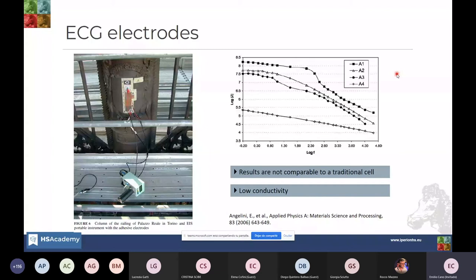And in this example, they use electrocardiogram electrodes, the ones that are used for medical studies. They were able to measure the impedance of the surface, and you can see on the right the modulus of the impedance. You can see that again they have been able to measure the impedance of different areas that have been cleaned by the restorers.